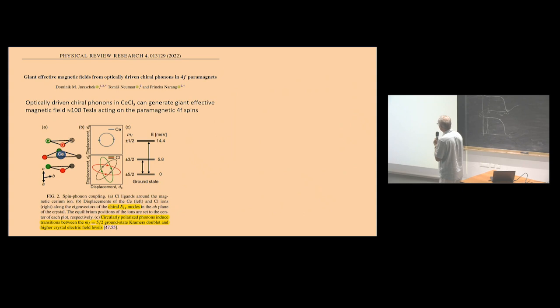And the point is that you can switch it very quickly, on a picosecond or sub-picosecond time scale. Another theoretical prediction, again from Juraschek, is about cerium trichloride. He predicted that if you pump the phonons in this system, you should be able to induce an effective internal magnetic field of the order of 100 Tesla, huge, just by pumping of phonons. Again, due to spin-phonon coupling, because in this case you have rare earths, cerium, and also this crystal field, and finally it can induce a really huge magnetic field.